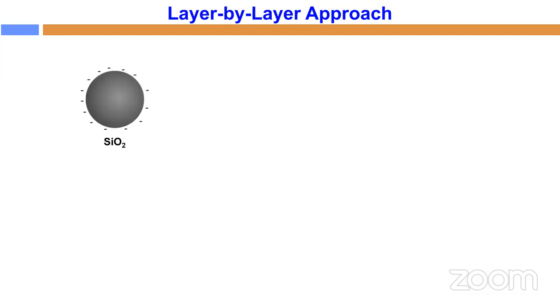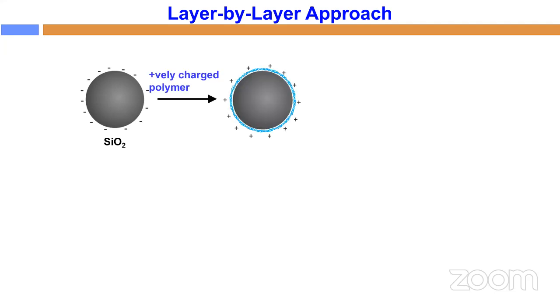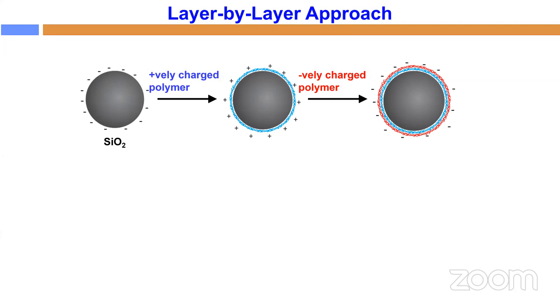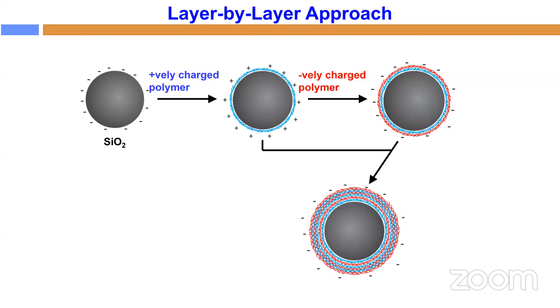The polymer capsule can be prepared by layer assembly. The silica has a negative charge. So we take the negatively charged silica and put it into the positively charged polymer, the polyelectrolyte. Because of the electrostatic interaction, the positively charged polymer adsorbs onto the negatively charged silica, and then we have the first layer. Since it has residual positive charges, we put it again into a negatively charged polymer. So we have another layer over that because of the electrostatic interaction. Now we have one positive layer and one negative layer. We repeat this process to build many layers. In this case, typically we did it for 8 layers.